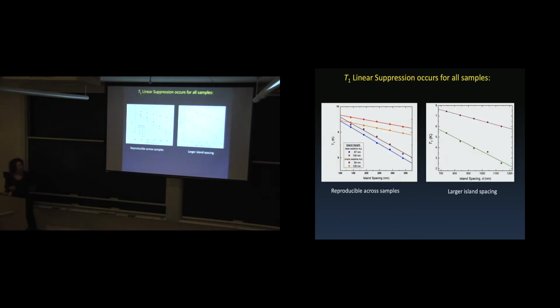Okay? If you plot this, you can see that the transition temperature of the islands actually varies linearly with the island spacing. Right? We see this for all the different parameters. We put it with different types of gold and different types of niobium, put it for shorter island spacings and larger island spacings. And in all cases, you can see TC keeps getting suppressed, but it happens linearly with island spacing.